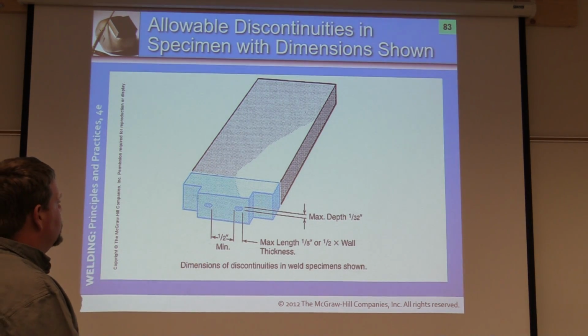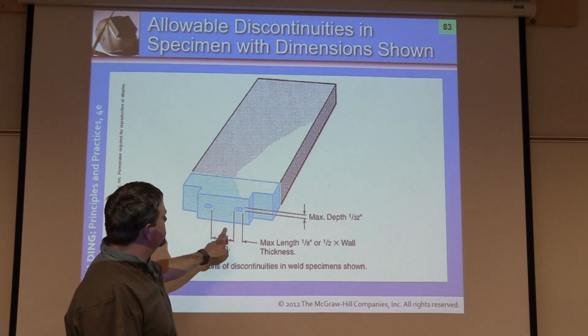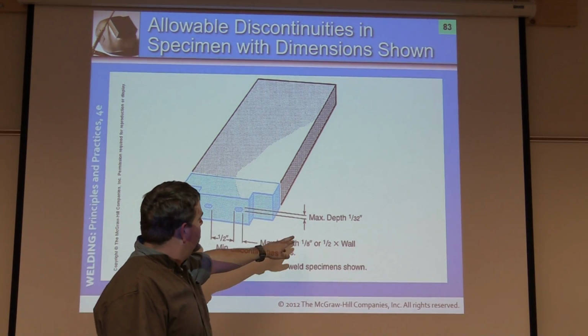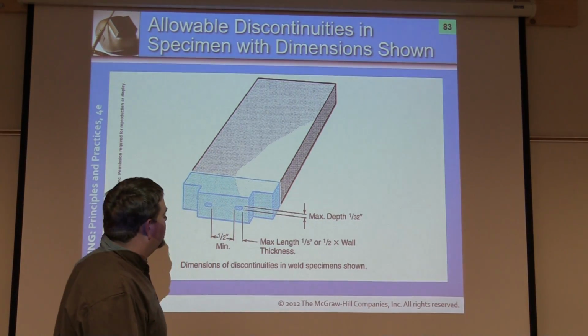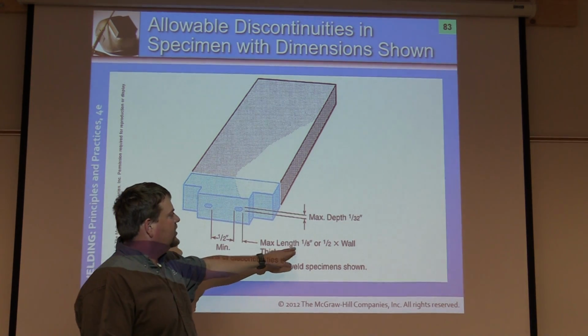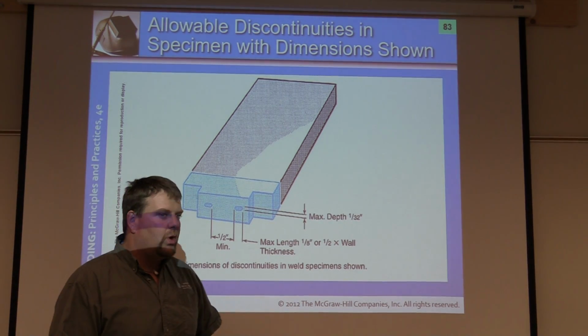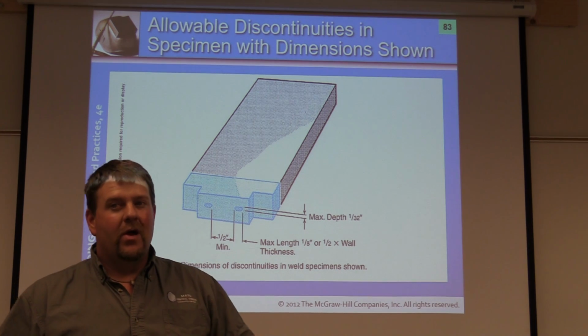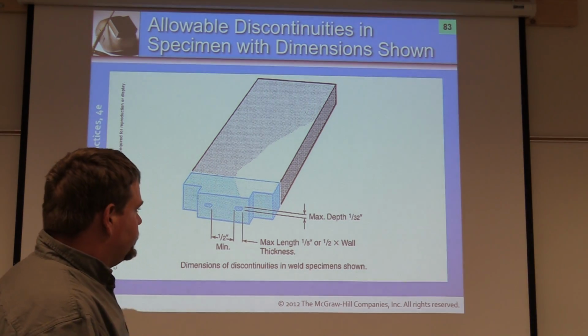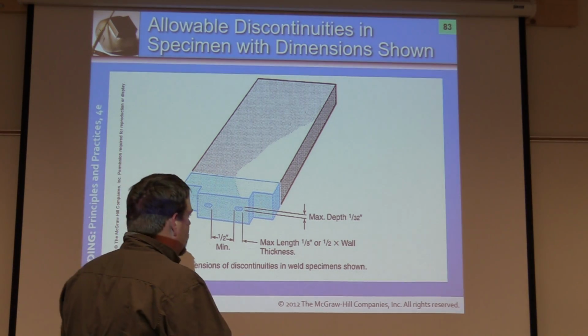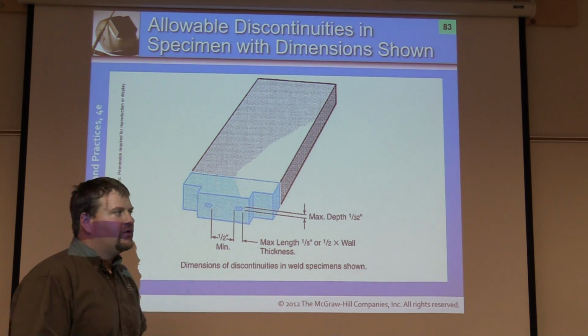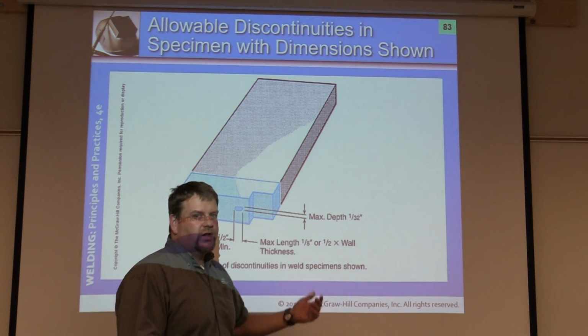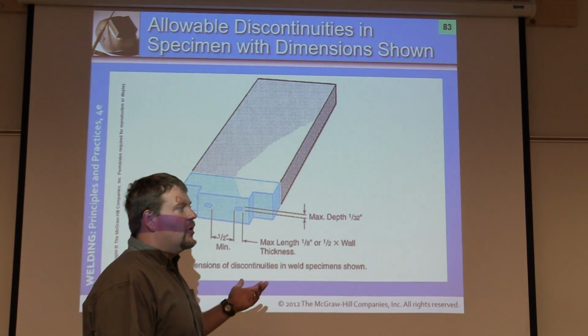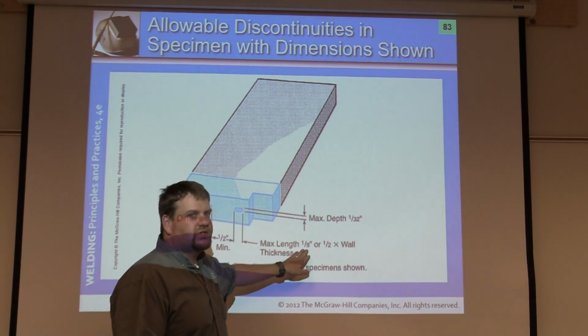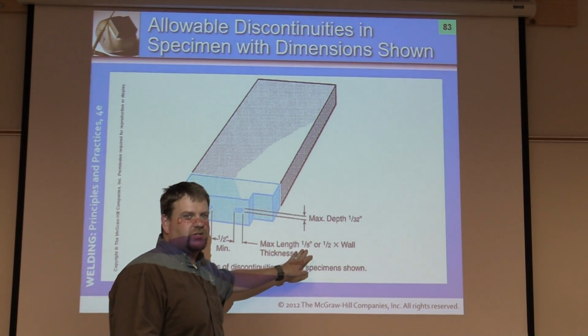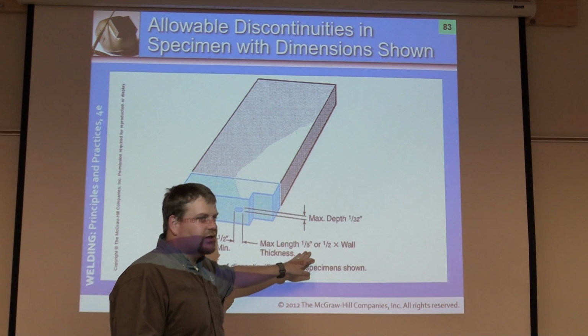Here it gives you discontinuities, so a 1/2 inch distance between the two. There can only be 1/32 deep, max length of 1/8 of an inch, or half the wall thickness. So, Schedule 40 pipe, depending on what wall thickness, let's say 6 inch, we're at 0.280. So half the wall thickness would be 0.140. 1/8 inch supersedes, it's a lot more strict. Since it's 0.125, we adhere to the 1/8 inch.